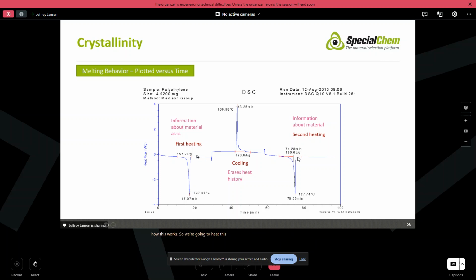So we're going to heat the sample up at a heating rate, typically 10 degrees C. We're going to control cool it again at that same rate, 10 degrees C. We're going to cool it down. And then we're going to heat it. We're going to heat it a second time. So the first heating run tells us about the condition of the material in which we've received it. So if it's just been molded in its as molded state, or if it comes back from the field in its state as which we've received it. That first heating run and the cooling run, well, that erases all of that heat history.